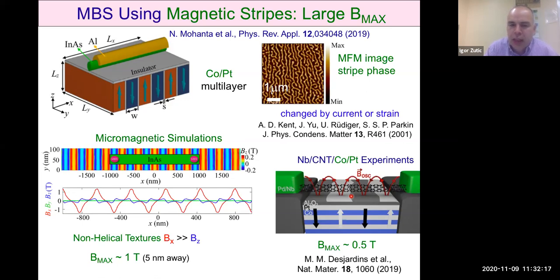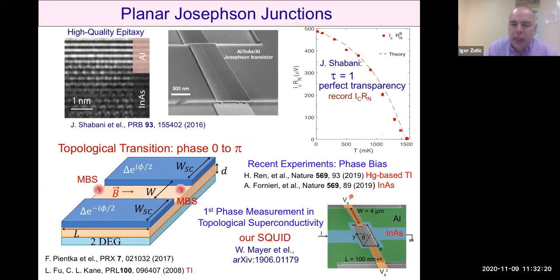There is also another class of systems where we don't rely on magnetic textures, we just apply magnetic field, and in variation of Josephson junctions or squid geometry, we can even see a direct signature of topological transition. So we can see a phase jump simply by controlling gate voltages in this squid geometry. And this may be the first experimental demonstration where phase across topological superconductivity or transition to topological superconductivity has been